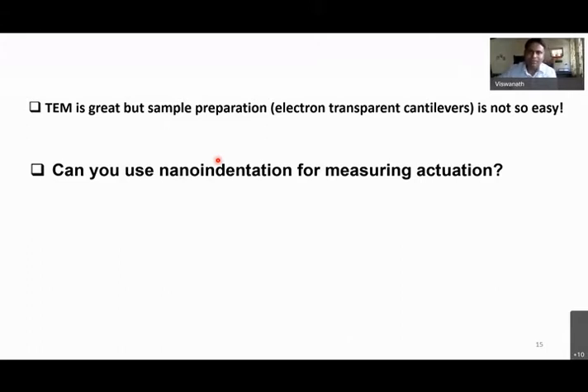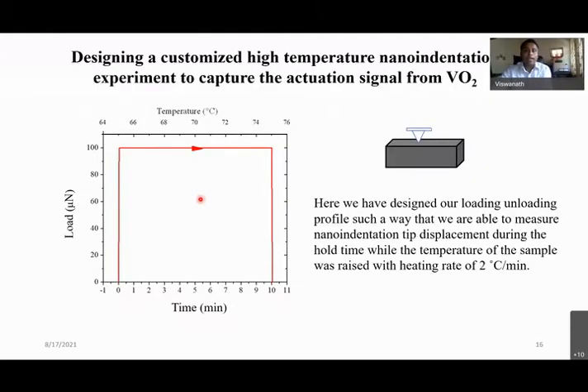But many of the bulk samples will have real difficulty in sample preparation, right? Making an electron transparent cantilever for many samples may not be that easy. So we are thinking, can we use some other methods like nano indentation for measuring that? It doesn't matter whether it is a single crystal, bulk crystal, or polycrystalline material. Without any thinning sample preparation difficulties, it'll be great if we can use nano indentation for actually measuring the actuation. That is what I'm showing here.